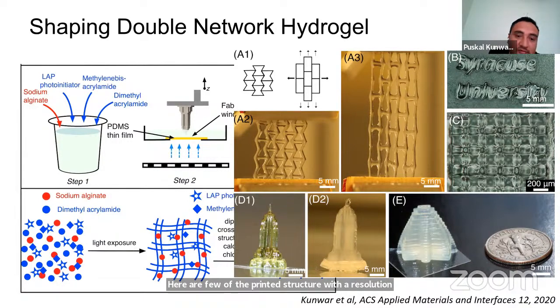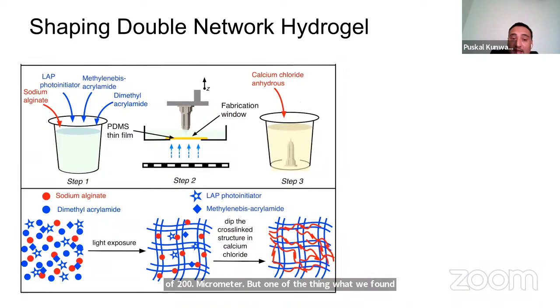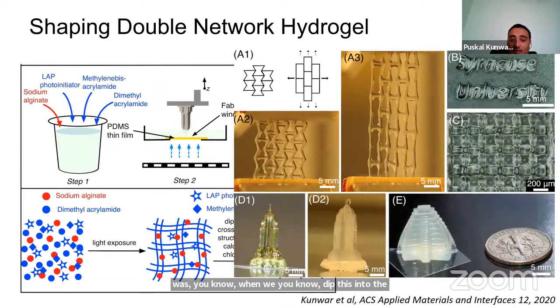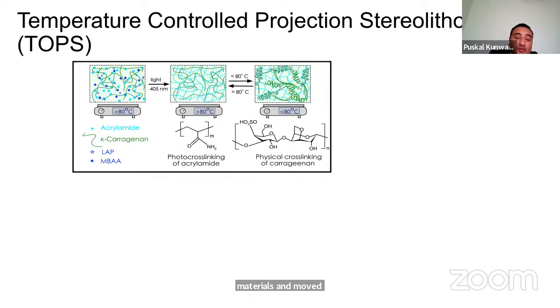But one of the things we found was that when we dipped this into the calcium chloride solution, our structure turned opaque. Now our aim is to make an optical component, so your structure has to be transparent. This was the first report of shaping double network hydrogel using PSLA, using both ionic and photo cross-linking methods. So we published this in ACS Applied Materials and moved forward to the next project, where we want to create a transparent 3D structure.